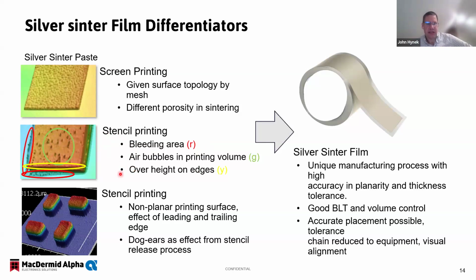imperfections in the surface. And then you can also get overheight on edges, where during the printing process the material tends to wick up, tends to start out low and then go high. I mentioned that here too in the stencil printing process, where you can see the non-planar printing surface. What happens is at the leading edge there's a little less material, and at the trailing edge there's a little more material. So that can be one of the non-desirable formats here.